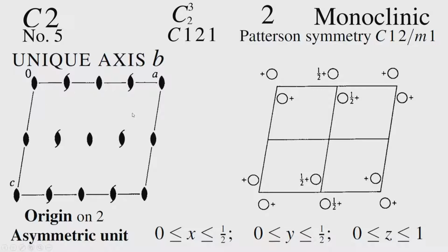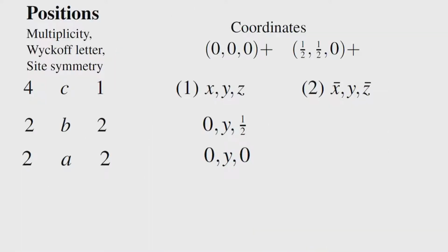If we look at the possibility of special positions here, interestingly special positions do develop. That is why I defined where the origin is, and once the origin is fixed, then the special positions will come at any value of y. So, the value of y is dependent upon where you fix the origin. The origin is fixed at the two-fold axis, then two special positions come up, and those are A and B Wyckoff notations, and these have two equivalent points, because the total number of equivalent points here, due to 0 0 0 and the two-fold and due to the presence of the C centering, is this, which we have already indicated in the diagram.